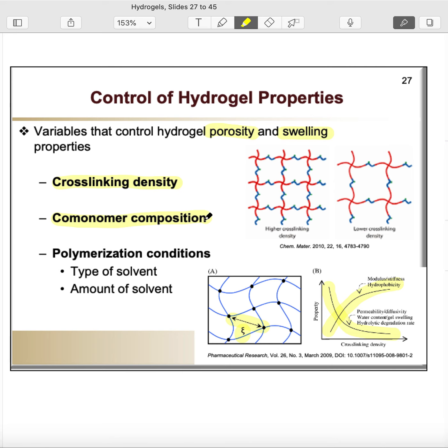At the same time, if your hydrogel is made from ionic polymers, the highest extent of swelling would be obtained if your ionic system is in its charged state and it's not neutralized. So if you have a polyanionic hydrogel that is chemically cross-linked, you're going to have a high swelling whenever the system is in its charged state. On the other hand, if you have something like a complex coacervate that has two different polyelectrolytes that are positively and negatively charged, then if you have a 50-50 molar ratio of the two, you will likely have the lowest extent of swelling compared to if you had something like a 75% to 25% molar ratio of the two electrolytes.